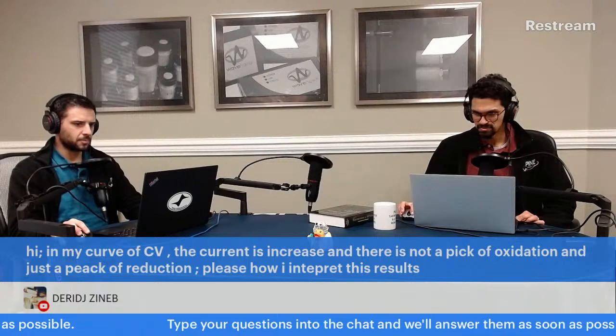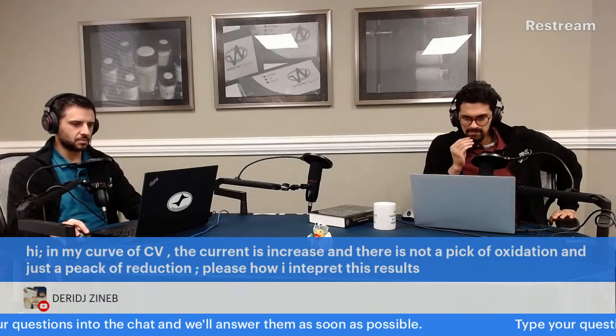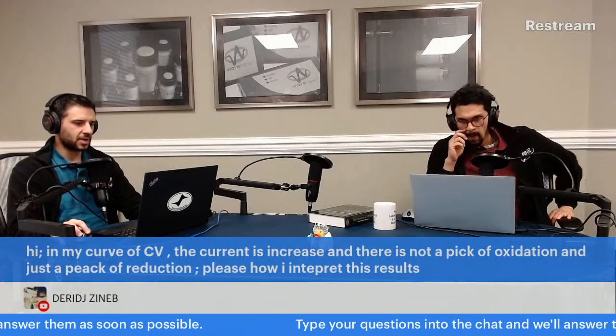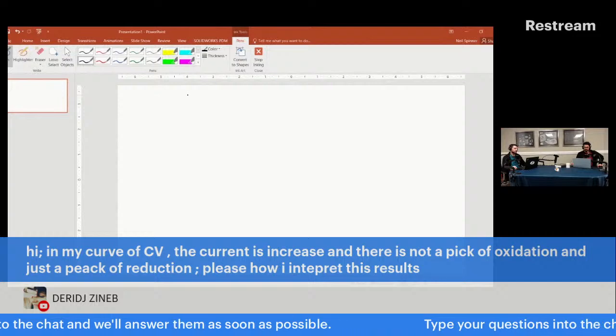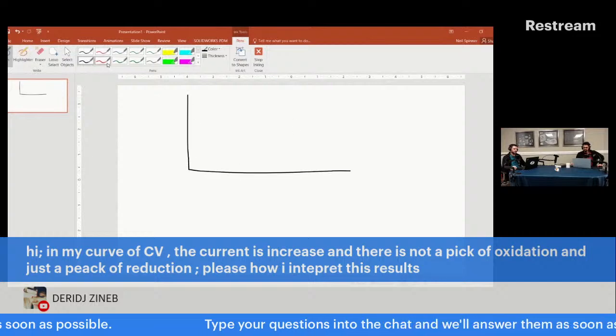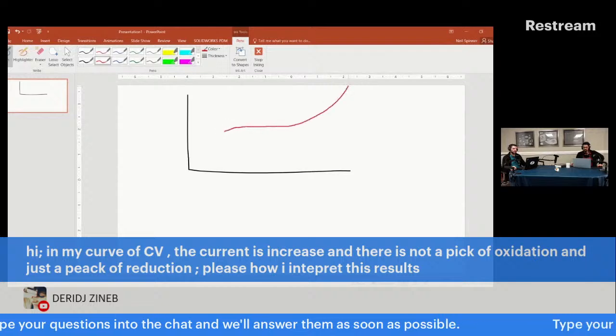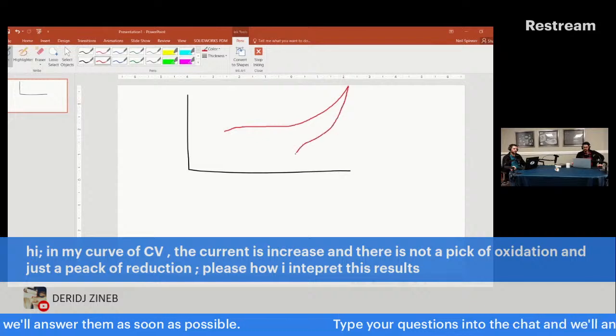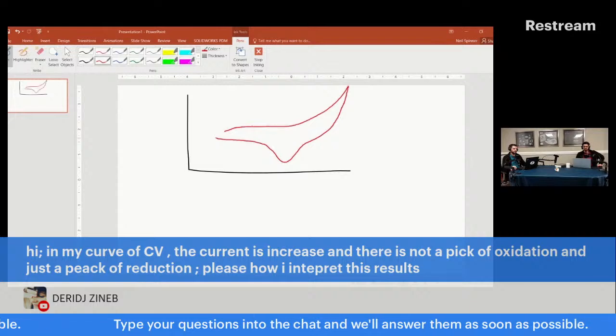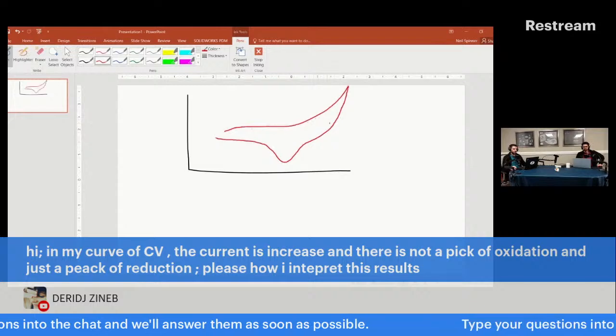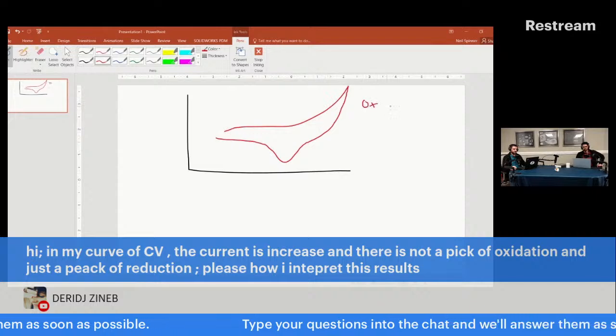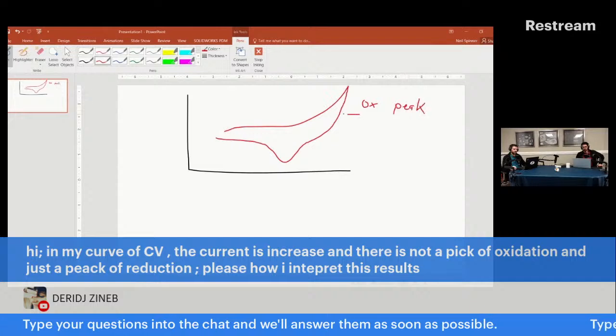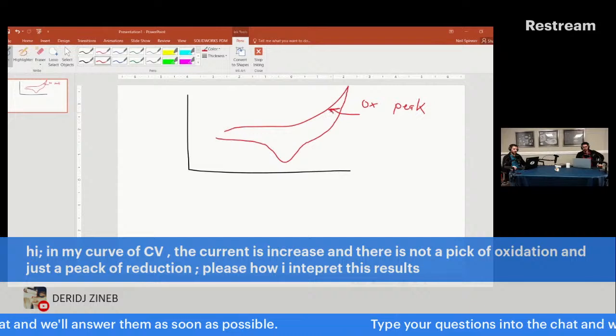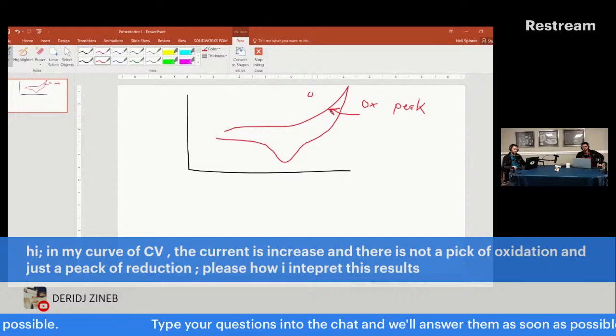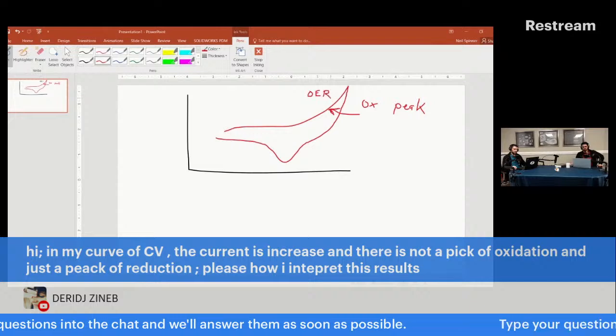I'll take this one. My ability to answer will be limited simply because I'm not looking at your data, right? But what I'll share with you is a possibility that I can maybe guess based on something that is plausible. So if I have a CV, for example, and I scan positive and I get a positive increase in the current, and then when I scan back, I get a reduction peak, but I don't have per se any oxidation peak, what it might mean is that my oxidation peak is in here. In other words, I am scanning very positively, probably to the extent that I have the oxygen evolution reaction, right? If I'm assuming, and I'm making a lot of assumptions here.